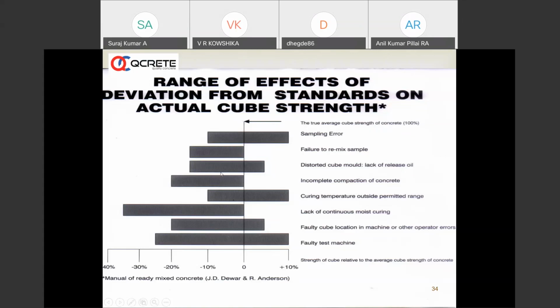Distorted cube mold. If the cube molds are not 150 mm by 150 mm, it may affect the strength negatively. Incomplete compaction has a very huge impact, minus 20%. Curing temperature outside the permitted range, sometimes it becomes negative or it can be positive.